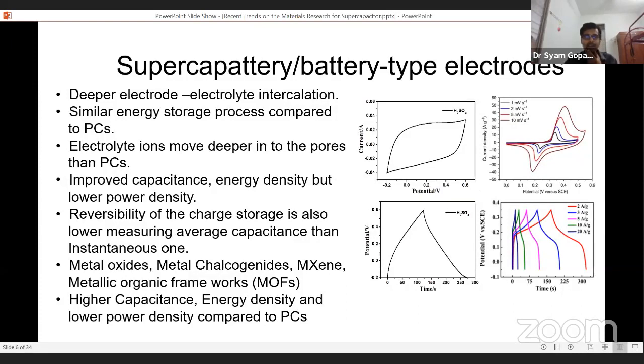Then comes the supercap-battery or battery type electrodes. I am just going to explain this concept based on the characterization technique of the electrode, that is cyclic voltammetry as well as charge discharge cycle. When we observe the cyclic voltammetry of a normal supercapacitor electrode, what we are seeing is an almost rectangular shape CV. In that case, if we take the instantaneous capacitance at each point, it will remain the same, and the average capacitance will be the sum of the instantaneous capacitance for this supercapacitor electrode. For example, activated carbon or manganese oxide or ruthenium oxide all come under this supercapacitor field.